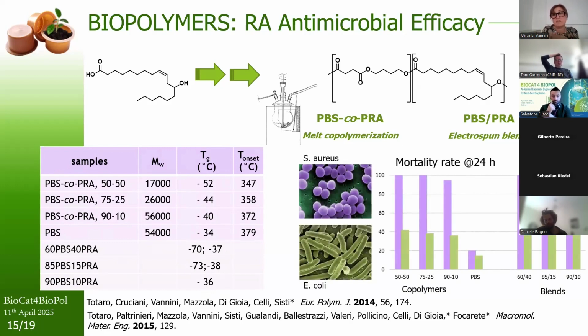Considering the antibacterial properties, all the materials result active against Staphylococcus aureus. The mortality rate is slightly low in case of copolymers for Escherichia coli, but the antimicrobial activity is very, very high for the blends, probably because PRA is more mobile, and therefore is free to exert its antimicrobial function.